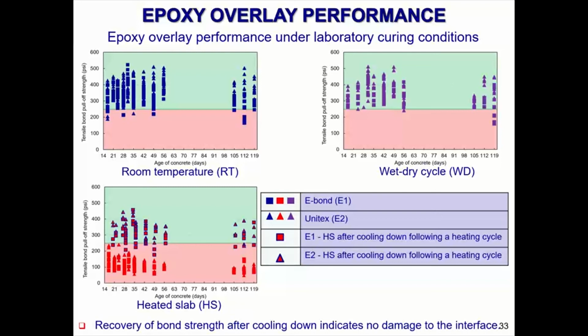In the upper right, you can see that nearly all of the slabs came back greater than 250 PSI in the pull-off test when they were tested after wet-dry cycles of a salt solution. But if you look at the bottom left, a lot of the slabs that were tested at 110 degrees Fahrenheit failed. They all failed while heated at 110, but then they retested them once they had cooled back down to room temperature, and they all passed again.